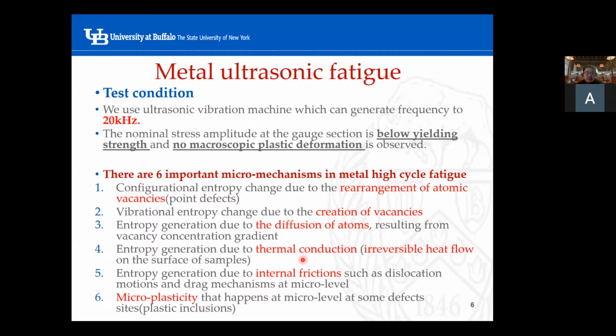For example, in conventional high cycle fatigue, the temperature difference between the center and the edge may at most be around 15 to 20 Kelvin. However, in ultrasonic vibration fatigue, the temperature difference can go up to 100 to 150 Kelvin. That creates a larger temperature gradient, and therefore the thermal conduction entropy production will be larger.